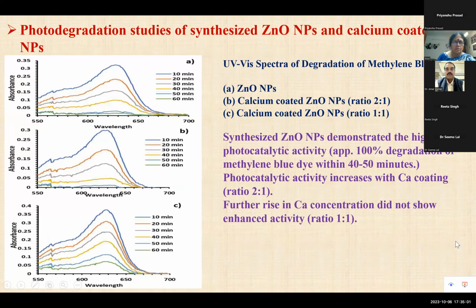Now, coming on to the photodegradation studies of synthesized zinc oxide nanoparticles, we did the degradation studies on two dyes. One is methylene blue and the other one is rhodamine B. But I'm showing only the degradation study of methylene blue. Photocatalytic reactions involve electron-hole pair formation by semiconductor nanoparticles. When irradiated with sunlight, the absorbed photons can cause electrons to be excited from the valence band to the conduction band to produce an electron and a hole. These species then generate oxidative species.